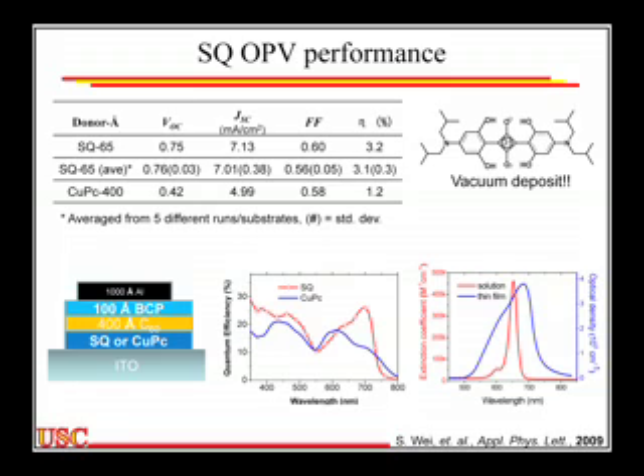You can see here the quantum efficiency as a function of wavelength, and you can see the photovoltaic quantum efficiency matches the absorption spectrum pretty well. She gets about 3.2% for 65 angstroms of material. So we're converting over 20% of the incident solar light into electricity with only 65 angstroms of the squaraine. Sort of gives you an idea of how big this extinction coefficient is. So I said, geez, if 65 angstroms is good, then more is better, and it turns out it's not.